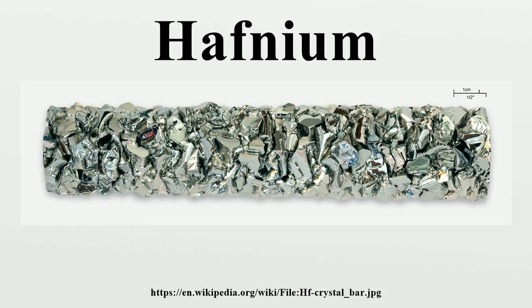Other uses, due to its heat resistance and its affinity to oxygen and nitrogen. Hafnium is a good scavenger for oxygen and nitrogen in gas-filled and incandescent lamps. Hafnium is also used as the electrode in plasma cutting because of its ability to shed electrons into air. The high energy content of 178m2Hf was the concern of a DARPA-funded program in the US. This program determined that the possibility of using a nuclear isomer of hafnium to construct high-yield weapons with X-ray triggering mechanisms, an application of induced gamma emission, was infeasible because of its expense.